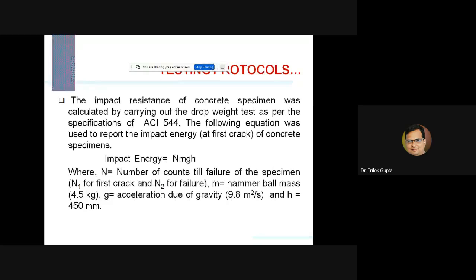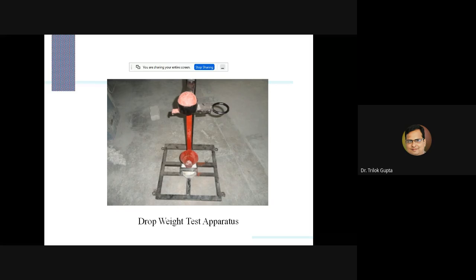After that, to find the ductile properties, we use the impact resistance by using the drop weight test, as per ACI, American Concrete Institute 544. This type of apparatus was used to calculate the drop weight. In this, we use cylindrical specimens having a diameter of 150 mm and a height of only 75 mm, and we drop the hammer ball, which has a weight of 10 pound, around 4.5 kg, and the height of fall or drop was 450 mm, 0.45 meter.